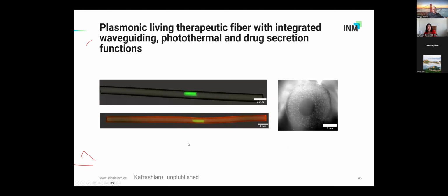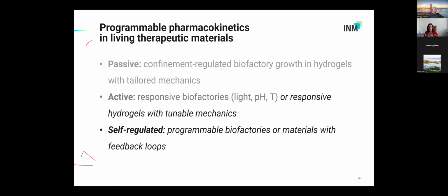And we are working now on the localized heating. We are not there yet to get it as localized as we would like it, but you see here that it works. So here you see a plasmonic element, for example, and here you see also that we were able to excite the bacteria that are able to produce a red fluorescence protein outside. We do not get the localization also because we do not have controlled temperature around, which is what we're working on. But the principle should work. So to summarize, this would have been the approach to get active response or active delivery or active control of the pharmacokinetics with light or with temperature using a living therapeutic material.